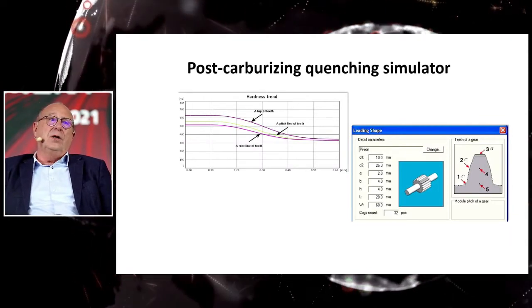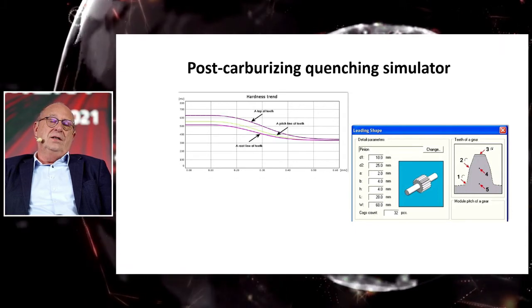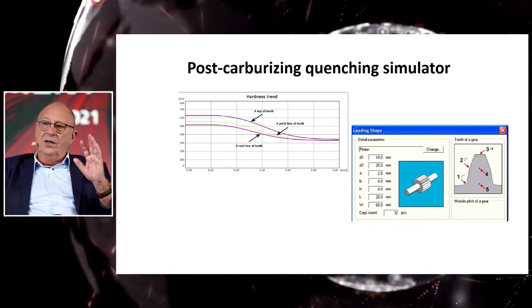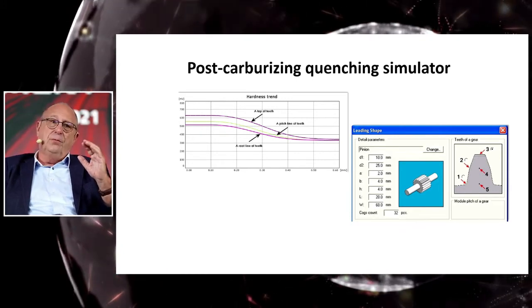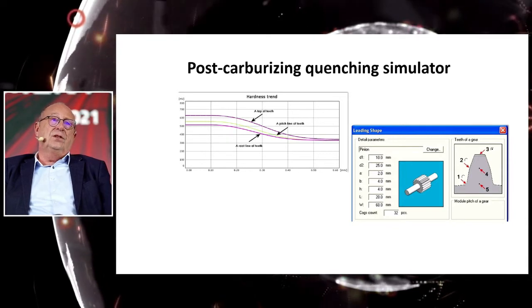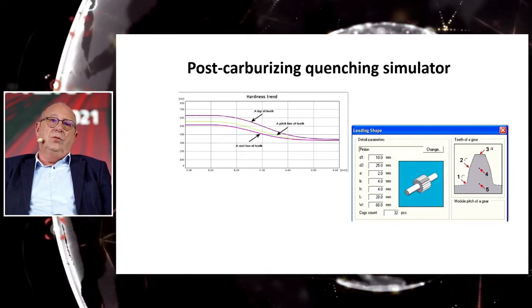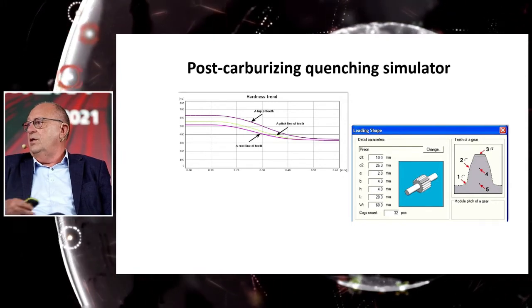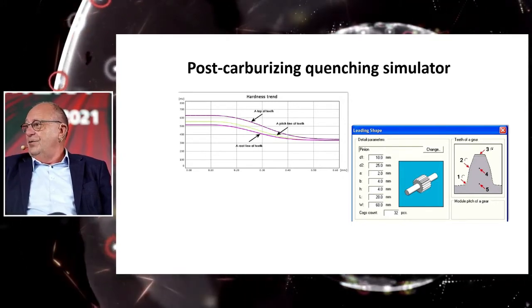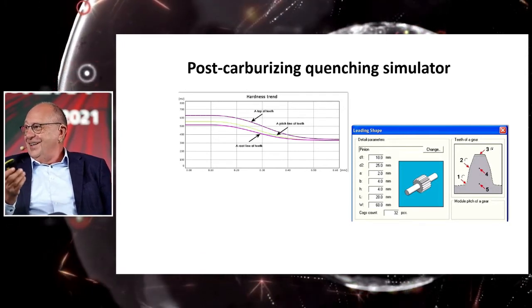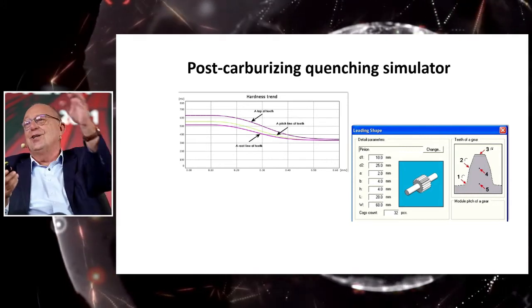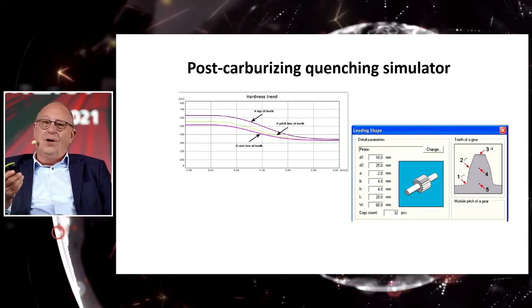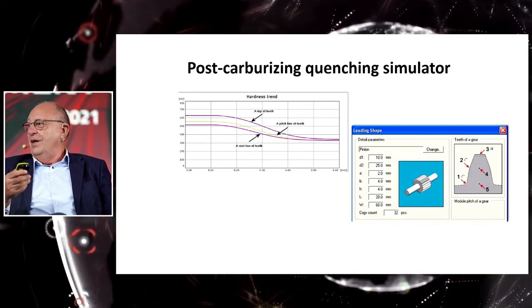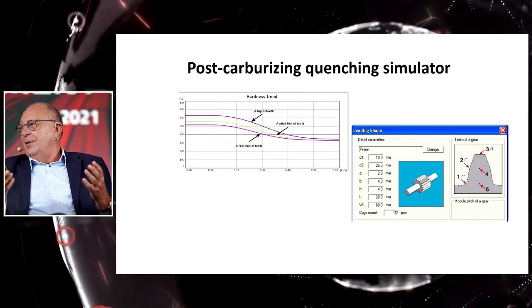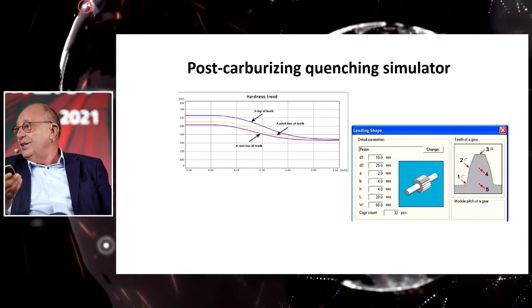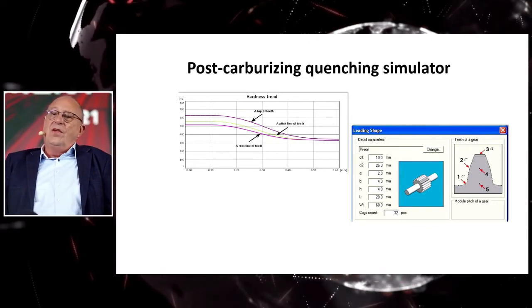So the next functionality of the SimVac program is the special dedication for gears. Gears are the important group of low pressure carburized cases. So the program helps us to simulate the differences in the carbon profiles along the tooth profile. It is very critical factor, especially for very important customers. They expect the homogeneous thickness, homogeneous hardness on a whole tooth. Of course, it is impossible, but this program helps us to find the compromise between the hardnesses, between the thicknesses of this case.